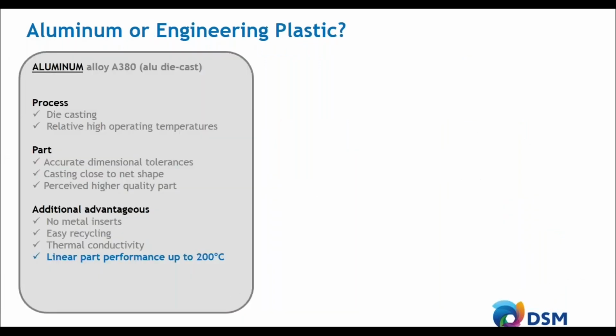As said, most of these parts are still in aluminum. So how to choose between an aluminum or an engineering plastic? If you take aluminum, for example, an alloy A380, which is commonly used in the automotive industry, you see quite some advantages of using this type of material. One of the key advantages is actually the linear part performance up to 200 degrees C. Of course, also after 200 degrees C, the strength and the stiffness of aluminum starts to drop. But up to 200 degrees C, you have a very good predictability of how your part would behave. That's often more difficult with engineering plastics.